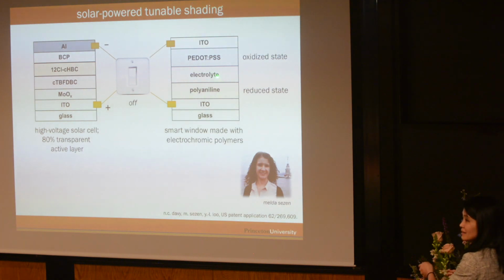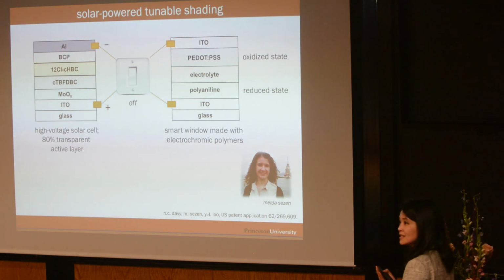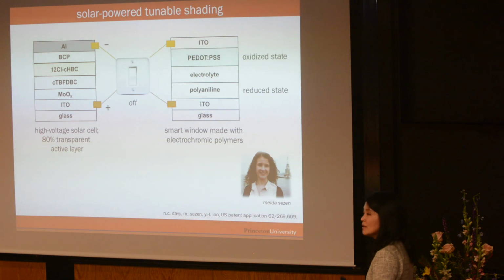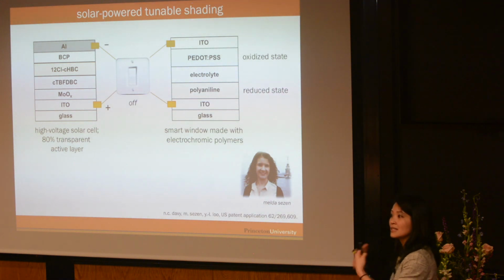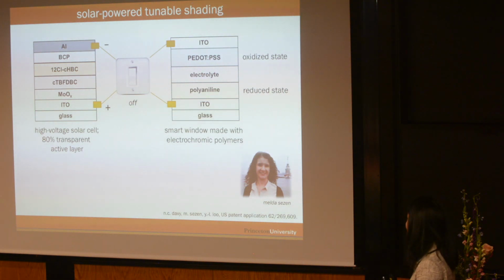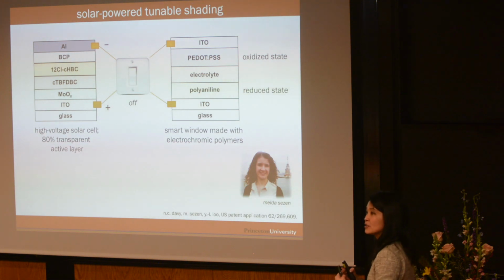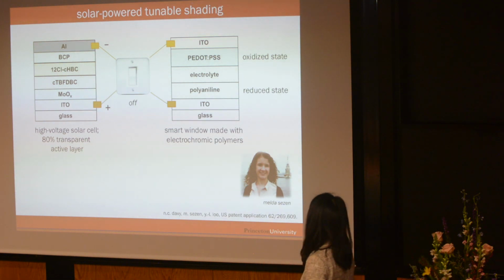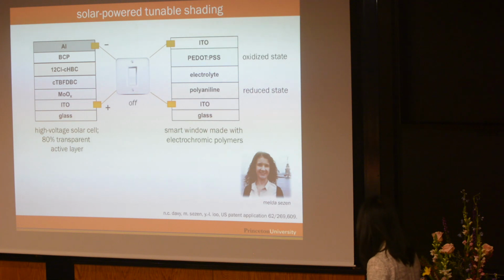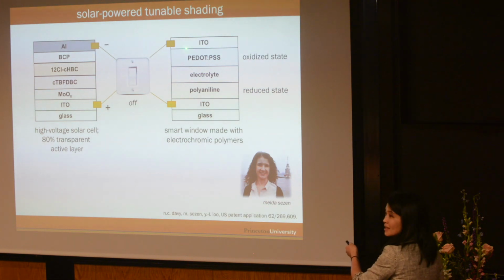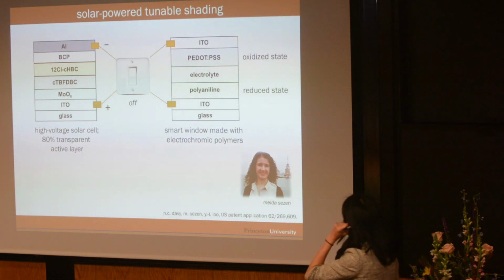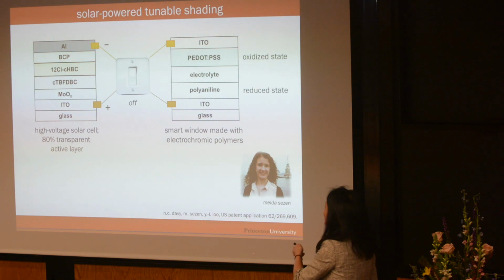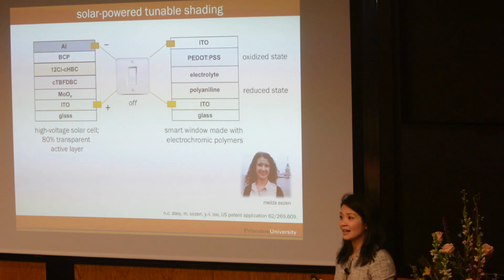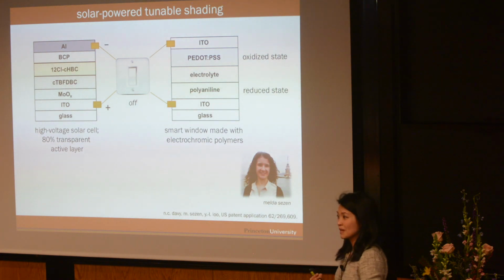We've got polyaniline, and we need a counter electrode, right? I've said that we're shuttling electrons back and forth, so we need a counter electrode that can accept electrons when we're shuttling them out of polyaniline, and we need one that can actually spit out electrons when polyaniline wants its electrons back. So we chose PEDOT:PSS, this is a common conducting polymer, because they're complementary, meaning that when polyaniline's reduced, PEDOT:PSS needs to be oxidized, and both turn out to be transparent, so you can enhance the transparency of your window.